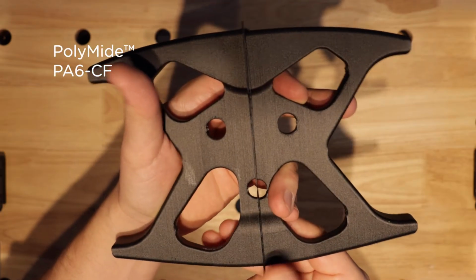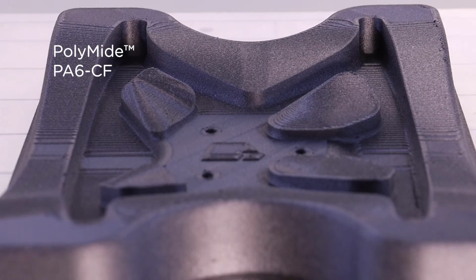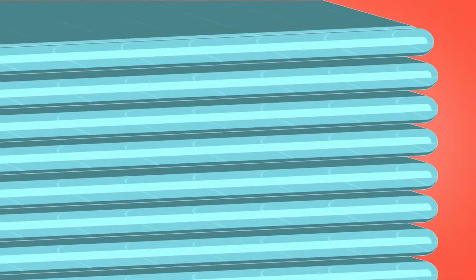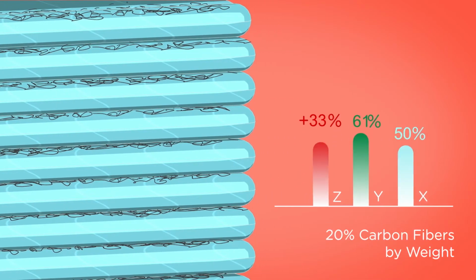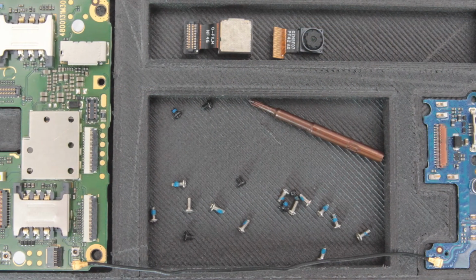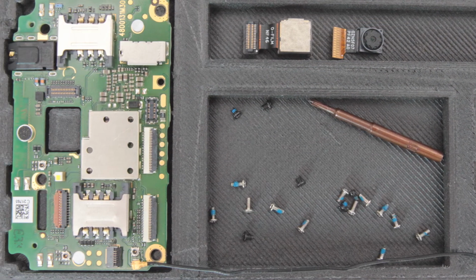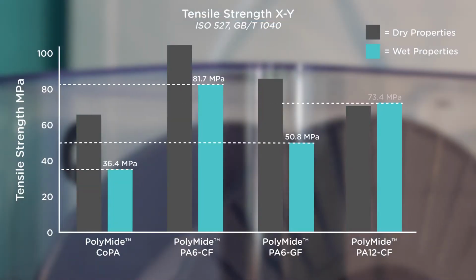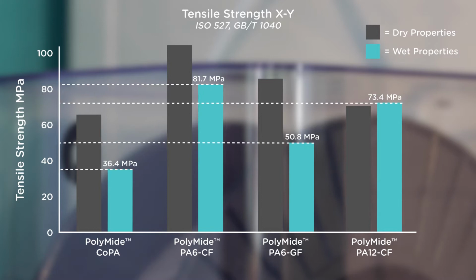Polymide PA6CF uses carbon fibers to reinforce the material and contains 20% CF by weight. The carbon fibers offer even more in terms of tensile strength, heat deflection and impact strength. The carbon fibers also help to lower the coefficient of thermal expansion to create a warp-free 3D printing material with incredible properties. PA6CF is also an ESD safe material, as the carbon fibers help to dissipate any electrostatic charge buildup. If you're looking for outright performance, then PA6CF is unmatched in wet state properties.